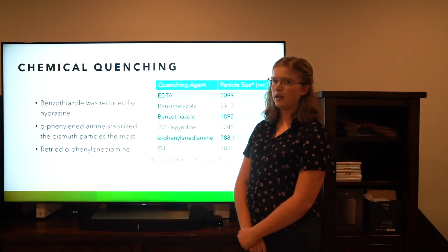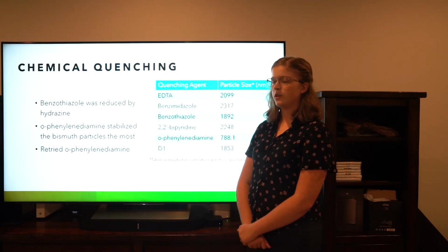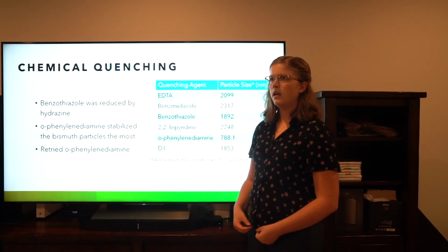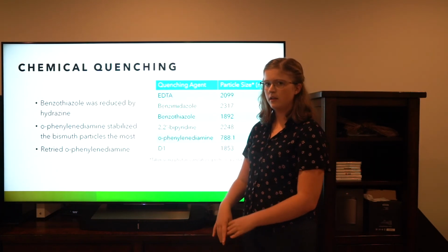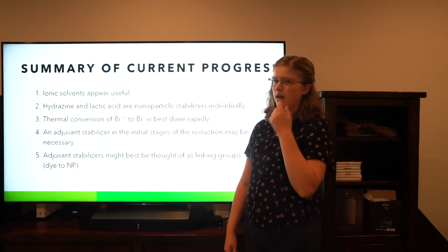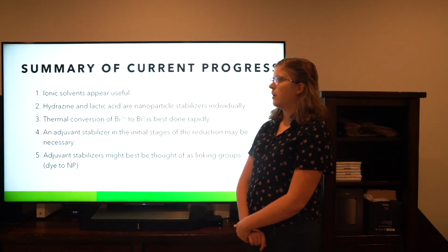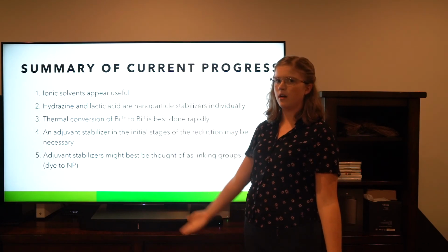When I did this, I created particles that were 2,547 nanometers in size, which was much larger than I wanted, leading me to believe that perhaps I should add stabilizer before heating so that each vial spends the same amount of time with stabilizer in it. Because of the COVID-19 pandemic, I was unable to continue my research, but based on what I've seen, this is a summary of my current thoughts.